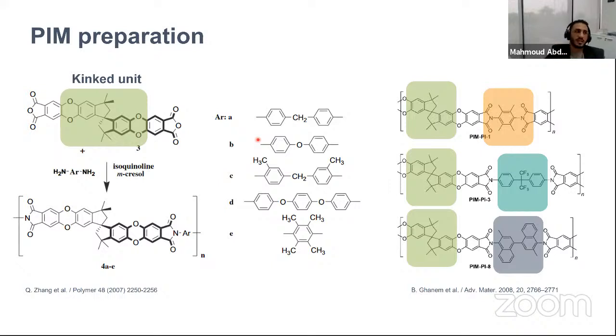Thus, we need something called a kinked unit. A kinked unit is mainly a non-planar unit. This is one of the most used examples here. It's called the spirobisindane unit, and it has a spiro center here. The presence of this kinked unit allows the formation of a porous polymer. And these are the first prepared polyimide-based polymers for gas separation applications.